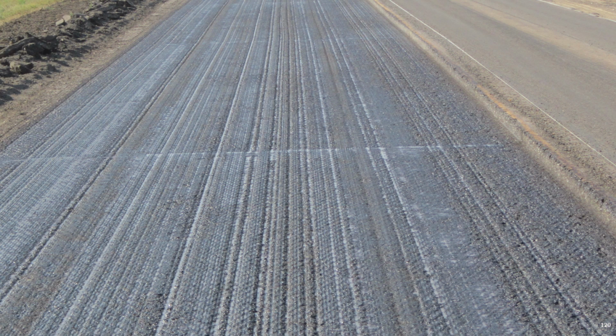Now let's talk a little bit more about tack coats. Tack coats are a vital component of an asphalt pavement structural system as they bond the multiple asphalt lifts into one layer. Poor tack coat applications result in poor bonding of the asphalt layers. This is an image of a milled, cleaned, and tacked roadway surface. When tack is sprayed on the roadway, it should be wet, shiny, and brown with full width lane coverage. After a short time, the tack will turn black. This is called broke. The surface will be dark in color with less sheen. The contractor will be ready to lay asphalt once the tack has broke.